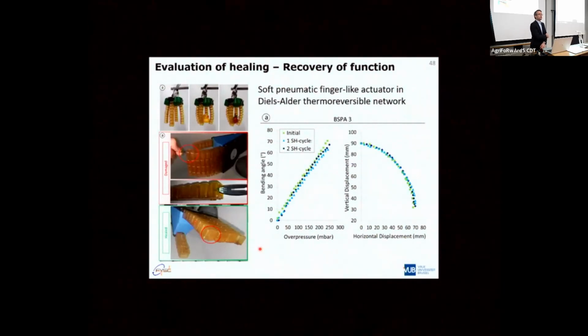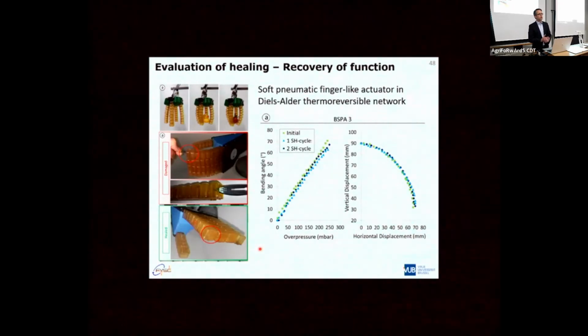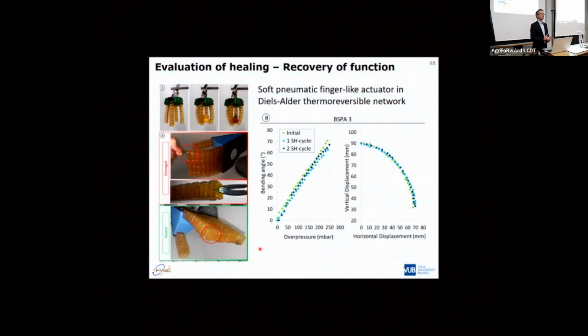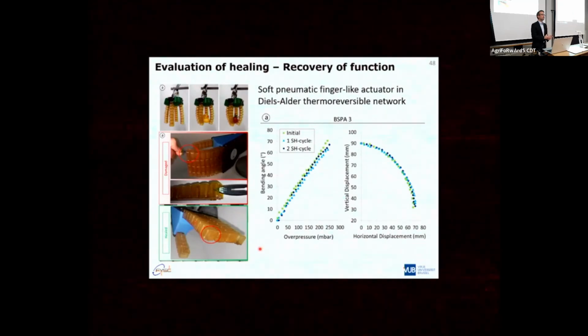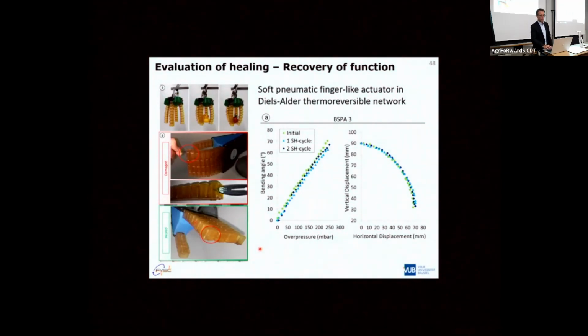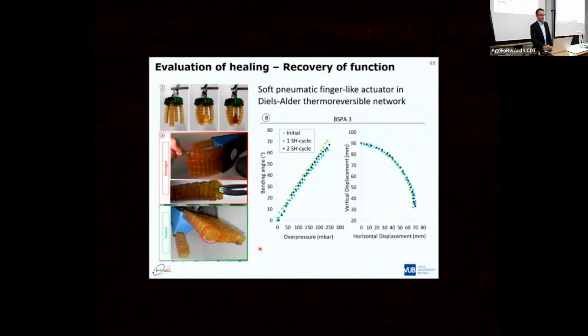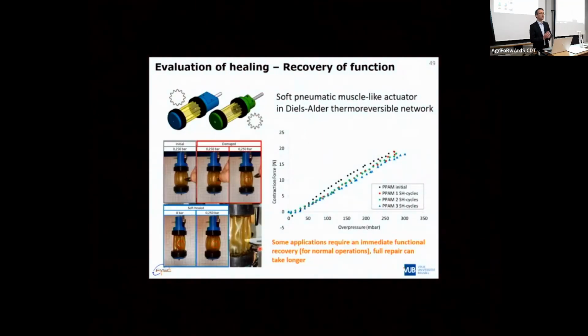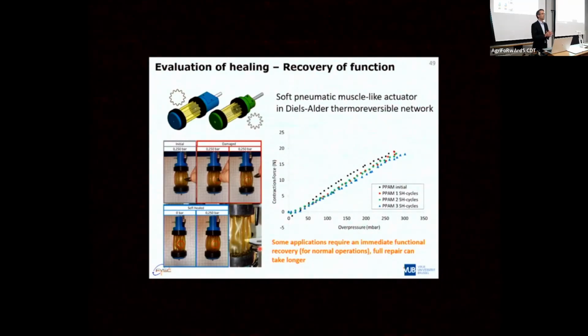But in the end, of course, for the robotics guys, the functional recovery is maybe the most important. You should take into account maximum operating pressures and so on, so that you don't limit the range of operation that you can use for your system by healing it in the wrong conditions. And then, of course, you need to test this for different kinds of damage. Don't only damage it in the easy places, also damage it in the zones of high stresses and high strains to get the more critical values.